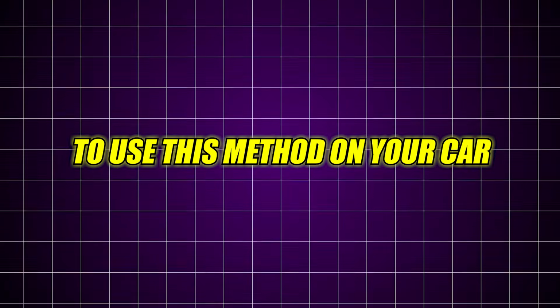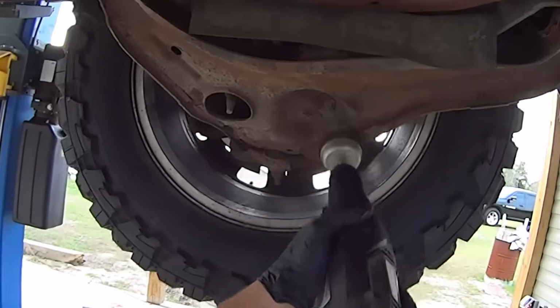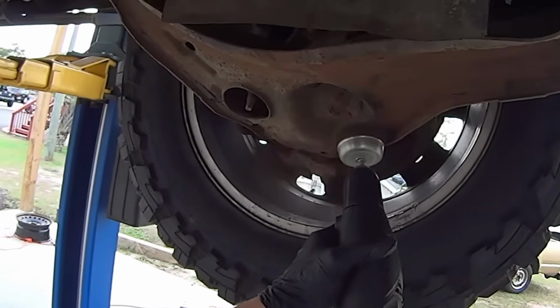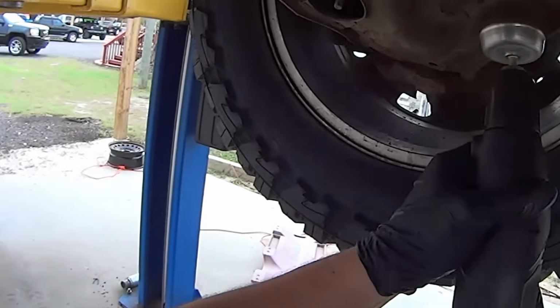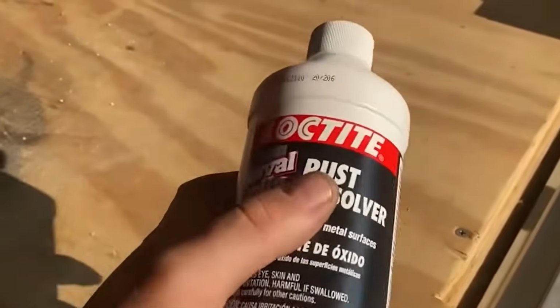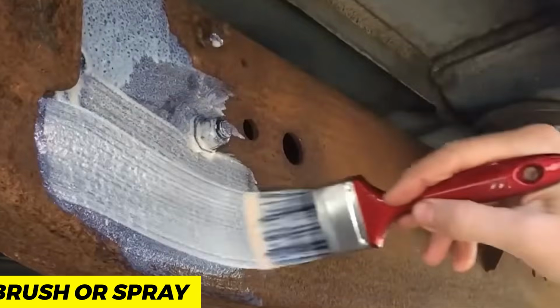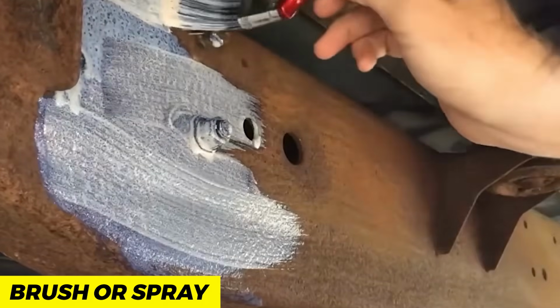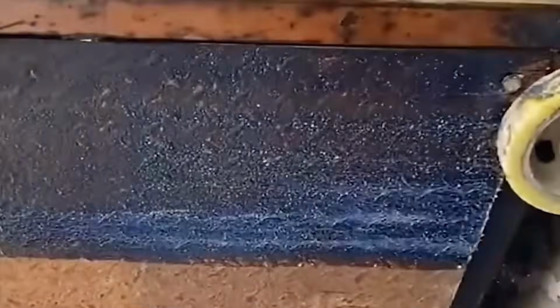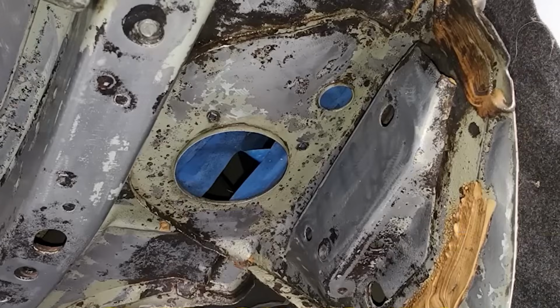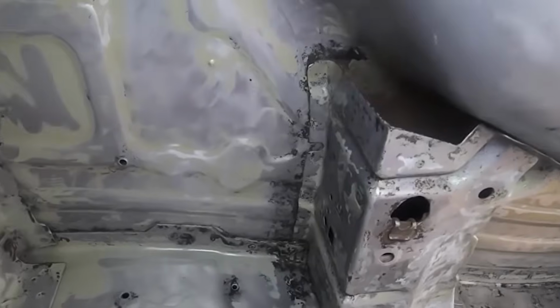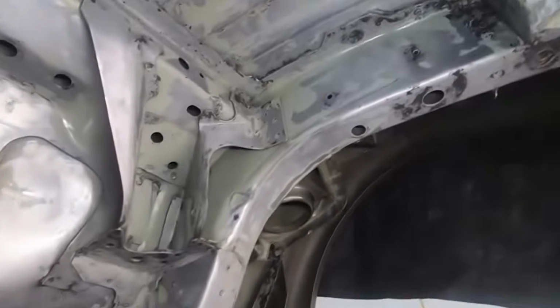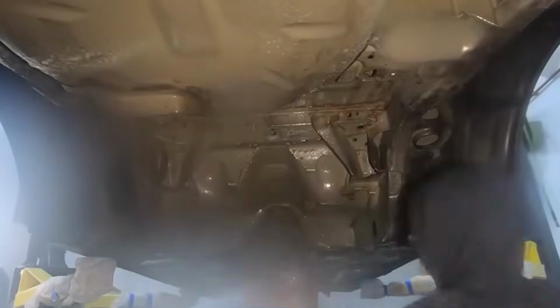To use this method on your car, first, clean the rusted area using a wire brush or sandpaper to remove loose flakes and dirt. Next, apply the rust converter using a brush or spray, ensuring full coverage of the affected area. As phosphoric acid reacts, it doesn't just kill the rust. It undergoes a complex reaction that transforms porous orange iron oxide into a hard, black, inert layer of ferric phosphate.